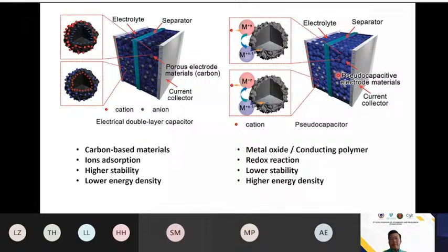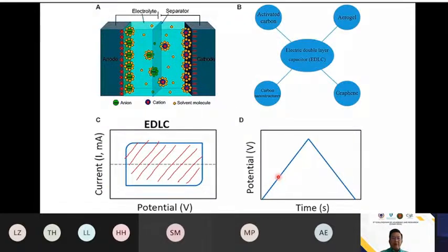So what is the difference between the metal oxide base and the carbon base? For the carbon base, the energy storage is only based on the adsorption of ions on the carbon surface. It can have very high ion adsorption, which leads to high stability, but at the same time it can only contribute a low energy density. Whereas in our topic, we are going to talk about the metal oxide. The mechanism for the metal oxide in charge storage is based on the redox reaction. The drawback is that it has lower stability compared to carbon, but the benefit is a high energy density, which meets our target today.